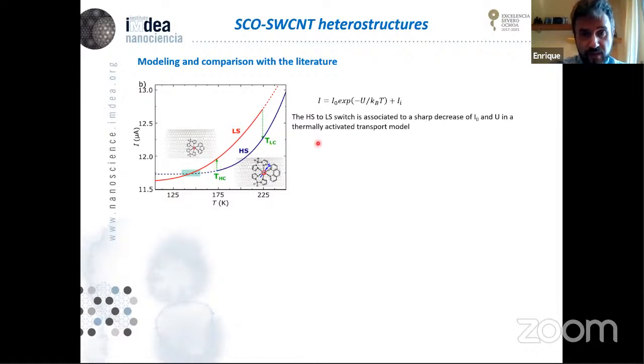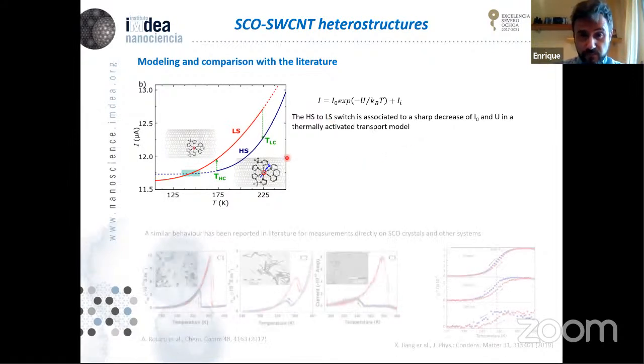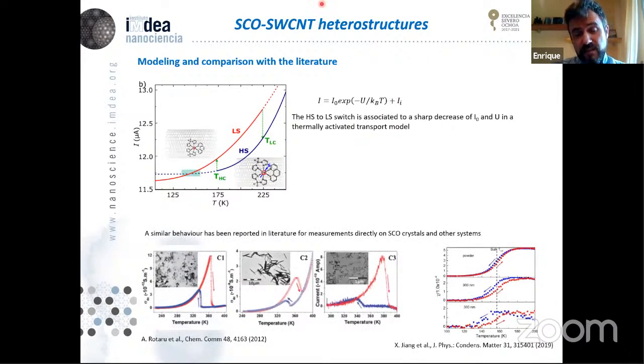Well, we could fit this with a thermally activated model with an Arrhenius law, and we see that this switch seems to be related to a really strong drop of the activation energy for transport across the carbon nanotube. This is actually something that has been seen before in measurements taken directly across the crystals, okay? So in this kind of crystals, they were putting some probes on top of the crystal, and you can see that they were seeing very similar hysteresis loops to what we see.